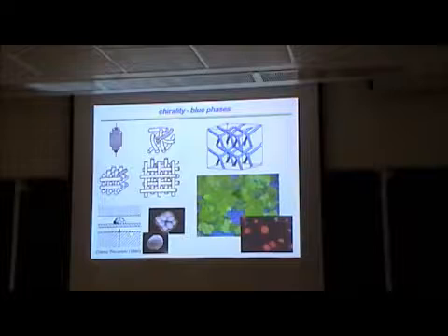In a temperature gradient, you can actually grow and visualize single crystals of this blue phase. Now, if you look at what happens to the director, you find that this kind of packing requires topological line defects. So this is a simulation of the line defects. It shows that they make kind of a double gyroid structure. They typically run along the 1-1-1 directions of these cubic lattices.